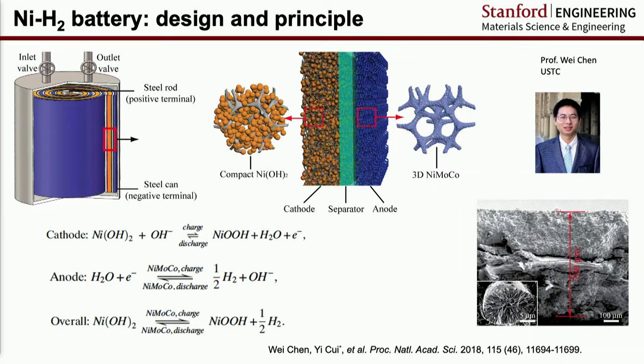As soon as I invented this, I got so excited. Then we looked into the literature and found out this is a forgotten chemistry. Actually, NASA has been using this for 30 years, and the Hubble telescope, 30 years, trouble-free. This gives me a lot of confidence. This is a very robust chemistry. But the NASA technology used platinum as catalyst, which is too expensive.